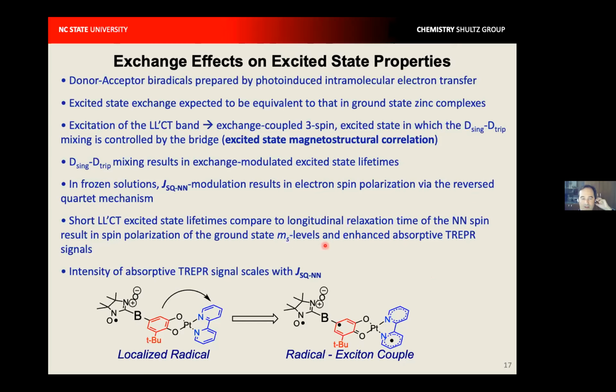Fantastic talk. Very interesting. I have a very short comment, maybe with a question. So I think when you compare the liquid solution Jablonski diagram and the frozen solution, there is one more difference, because these transitions from the doublet state to the ground quartet state are in fact weakly allowed due to anisotropy of the exchange interaction. So in frozen solution, you have this anisotropy. In liquid solution, when your molecule rotates very fast, there is no anisotropy, of course. So maybe this adds some more effects and enhances the efficiency of these transitions. Yeah, maybe not. Just an idea.